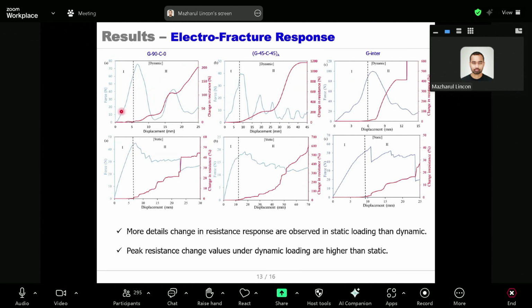In stage 1, no electrical change is observed because in this stage almost insignificant damage happens in the specimen. This black dotted line shows the crack initiation point. After this black dotted line, every specimen's change in resistance increases gradually.